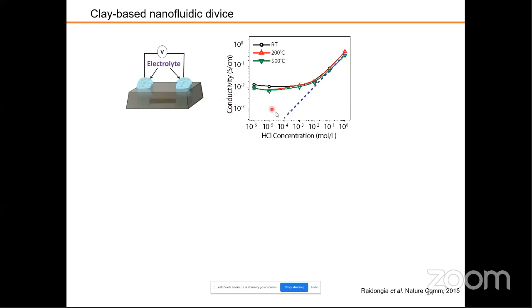We can see that if it is not a nanofluidic channel, the conductivity should behave like this blue curve, because, as students probably study at BSc level, the ionic conductivity is directly proportional to the number of ions present in the channels. This is how the blue curve looks. But inside a nanofluidic channel, it is not directly proportional to the concentration. After some time, it is stable. Even though we are changing the concentration from 10 to the power minus 3 molar to 10 to the power minus 6 molar, the conductivity did not change. It remained constant throughout the concentration range. And this is the nanofluidic phenomenon.